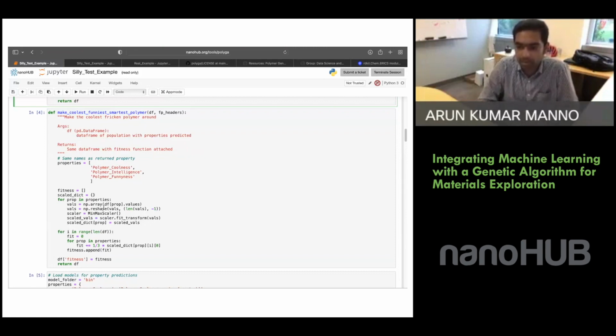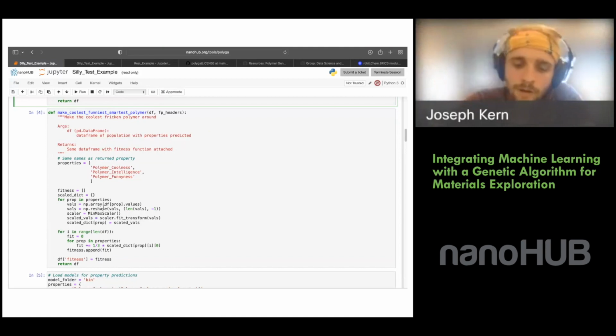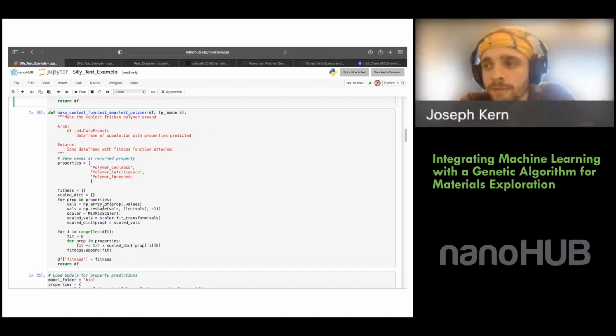Question by Brett Henderson: very cool work. Is there a reason why you don't include polymer length in your fitness function, or is it something you may want to constrain? I've experimented with this, and in my paper, I talk about this. You can constrain the length, so you can make polymers that are only 4 blocks. When I do the splitting, there's a hyperparameter you can add where you can either just split in the middle, so all polymers are only 4 blocks in length, or you can let it grow naturally. That growth depends on the mutation rate you choose for your children. And if you constrain it at the maximum, so you say it can't be bigger than 6 blocks, for instance, you can absolutely do that. And I've done that.